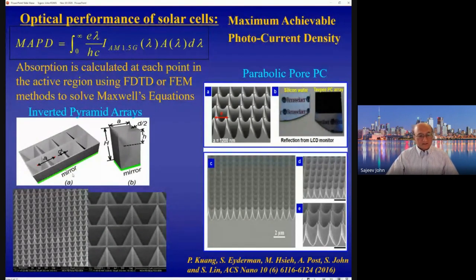And two of the types of structure that we focused on recently are shown here, mainly because of the ease of fabrication. One is an inverted pyramid type structure, which can be created by wet etching on the surface of silicon, namely a potassium hydroxide etching process, which preferentially exposes the 1-1-1 surface of silicon if you start with a 1-0-0 surface, and you can create these nice inverted pyramid structures. This is something that was created at the Melbourne Center for Nanofabrication using wet etching and electron beam lithography.